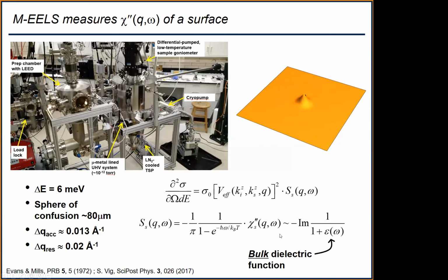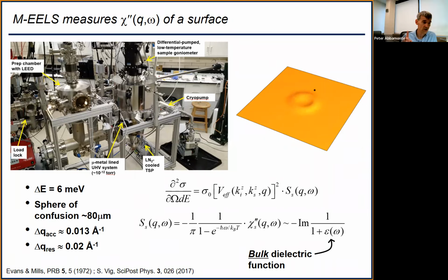So what is the penetration depth? Like one layer or how many? Good, I was hoping you were going to ask. The probe depth. I called it a surface technique, but it's not really surface. The probe depth is basically given by the inverse of the in-plane momentum transfer. So if you measure at a Q of 0.05 reciprocal lattice units, then you probe the inverse of that in lattice parameters into the material, which would be 20 lattice parameters.